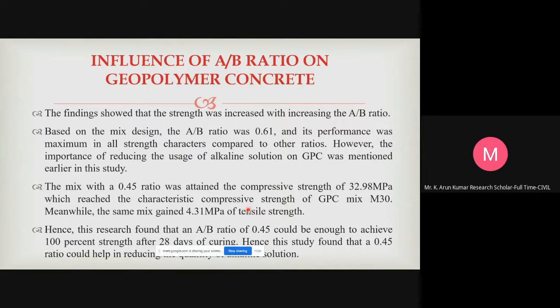However, the importance of reducing the usage of alkaline solution in GPC was mentioned earlier in the study. The mix with the 0.45 ratio has attained a strength of 32.98 MPa, which is more than the characteristic compressive strength. Hence, we can choose 0.45, which is enough to achieve 100% of strength after 28 days of curing. So the study found that a 0.45 ratio could help in reducing the quantity of alkaline solution.